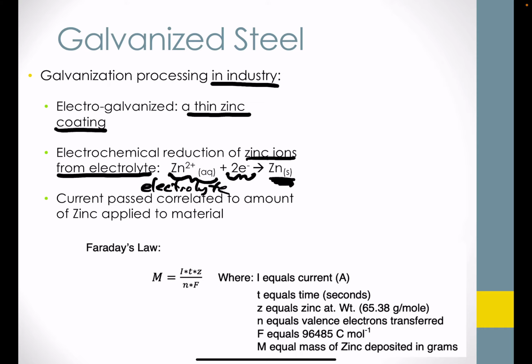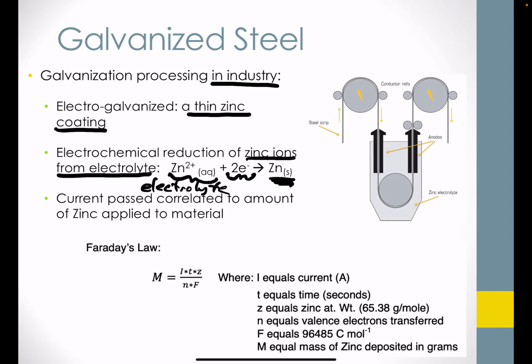So long as the structure is conductive and we can connect leads or wiring to it, we can consider applying zinc as a uniform coating around it, wherever the electrolyte has enveloped the metal. And so a process here where, say, a steel belt or strip is passed through rollers that are acting as an electrical contact point, can bring that steel strip into the zinc electrolyte that we see here. So this is a bath of zinc electrolyte. Some anodes complete the circuit. So the anodes are shown here. The steel strip is acting as the cathode as it passes into the bath.